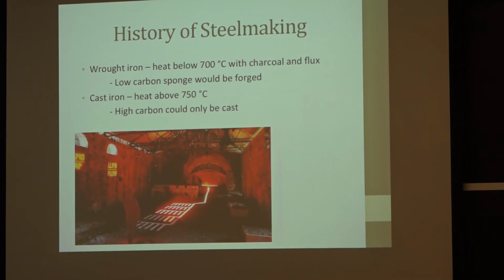Yes? So if it's only at 700C, is it just diffusion? Oh, I'm going to talk about that. Okay. Well, it is a diffusion process to smelt it. You don't melt it. You actually take the iron ore, put it in with a bunch of charcoal, put it in an oxygen depleted environment, and you get a reducing carbon monoxide atmosphere, which reduces, and you get sponge iron. You basically get something that looks like a sponge. It's all porous, and you have to forge that back into a solid chunk. And you lose 50% of it by oxidation in the forge, okay, as you're pounding it to get all the pores out of it. But it is a solid state process at 700C.